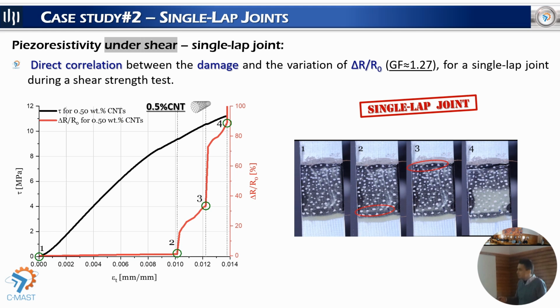This moment 2 corresponds to the first increase of the electrical resistance in the measured value. And here, the moment 3, again, we have the beginning of the fracture on the opposite side of the joint. It also corresponds to a marked increase of the electrical resistance. And the final break of the joint corresponds to the infinite increase of the electrical resistance. So once again, the real-time monitoring of the structure, in this case a single lap joint, with the control of the electrical resistance, can give us an idea about the integrity of the joint.